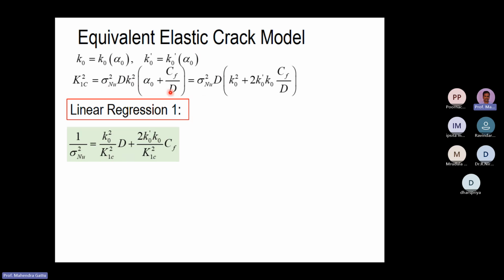So the basic equation, we are doing a Taylor series expansion, and we're getting this, and we have the data for peak load and the size, and using that we can find out this slope and the intercept. Once we know the slope and intercept, we can calculate KIC and CF value, because K naught and K naught prime we can calculate using FEM or the stress intensity factor handbooks. So this is the basic gist. This is the equation which will be used to analyze our experimental data.